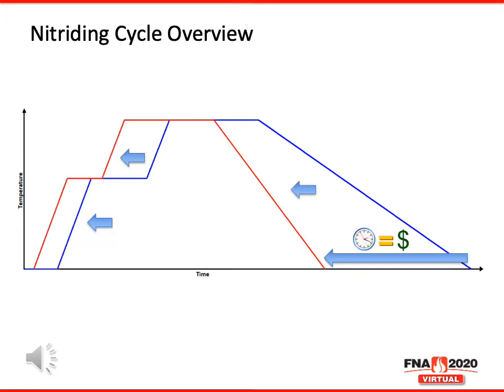So what if we can take that time and temperature profile and shift it to the left by reducing those purge times and cooling times to create an overall shorter cycle? Our nitriding time itself is the same, but now those times before and after those steps have been reduced, to help us improve that overall cycle time.